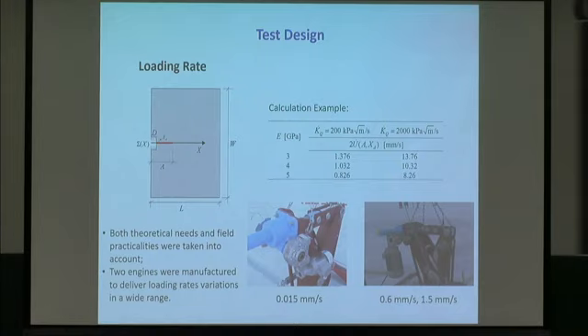Another thing I would like to say is also that I'm very much in favor of a stiff system when we are testing, and we know that there are several jack loading systems based on hydraulic systems. If you should do that properly, you should probably need to have a closed loop for the feedback and so on. So I've always gone for screw jacks with a high capacity, for instance from this engine here until the loading device, which is below here. We have a gearing of 1400, so I actually could turn this more or less with my finger, and in that case I know it will be quite stable in the speed, or I could say independent of load. So we had speeds here from 0.015 millimeter per second to 0.6 to 1.5, so a factor of 100 here from the lowest to the highest.